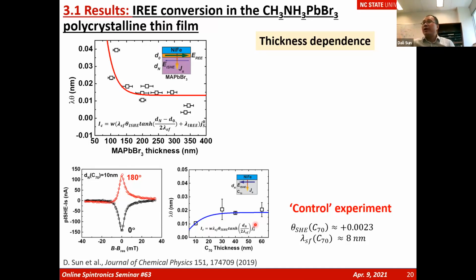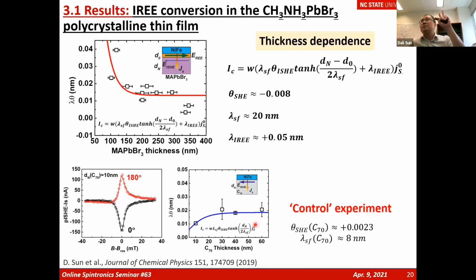That gives us the motivation that the spin-to-charge conversion contains two parts. One is the surface state, which doesn't change as a function of thickness, which contributes to λ_IREE, and is always there. The second is the bulk effect, but its spin-to-charge conversion relation is negative. So it means a negative spin Hall angle, which is consistent with our measurement in MAPbI3, which without a strong Rashba state shows a negative spin Hall angle. That validates our hypothesis that the spin-to-charge conversion in the MAPbBr3 thin film contains two contributions: one from the bulk, a negative contribution, and one from the surface, which is positive, a large spin-to-charge conversion that may be contributed by the Rashba effect.